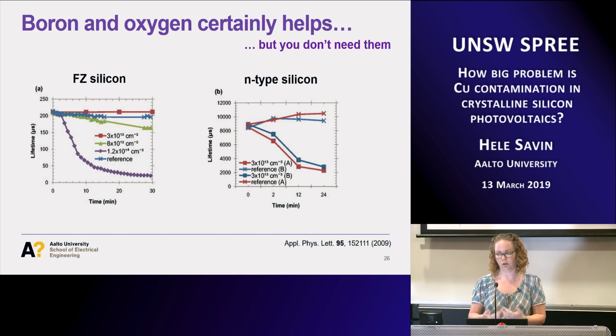I also have to say that all the previous experiments have been done with p-type wafers with boron as a dopant. So we wanted to be sure, because you are aware of the boron-oxygen LID, how boron and oxygen are related to the copper LID. So we repeated the experiments with samples which do not have any oxygen. We take float zone silicon, and what we see there is that yes, we actually see copper LID, but it's much weaker, or you need a much higher copper concentration to start to see the degradation. All the levels up to 8 times 10 to 13, you barely see any degradation. So float zone is really insensitive to the copper. You don't need oxygen, but it certainly makes this reaction better.